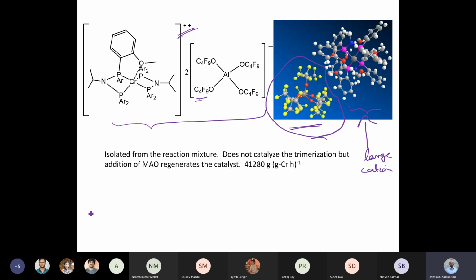And this was the hypothesis to start with, that the large anion will not be able to approach the transition metal, which is actually functioning as a catalyst, and olefins would be capable of interacting with the transition metal and carrying out the oligomerization. And interestingly, if you add MAO, this regenerates a catalyst. This isolated species itself is not a catalyst. Okay, it does not catalyze trimerization, but you can regenerate it.